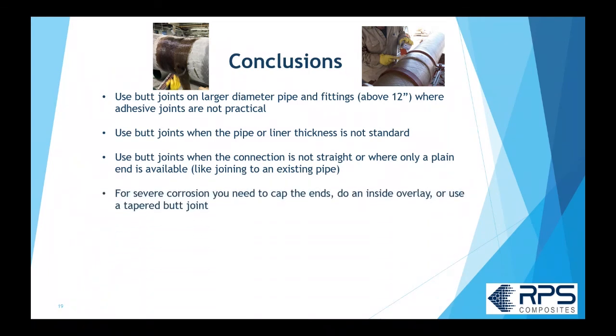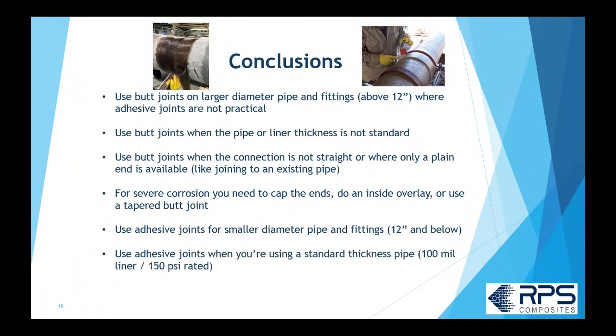If you have severe corrosion, you probably need to cap the ends or do an inside overlay or do a tapered butt joint if you're going to use a butt joint system. Adhesive joints are more practical on small diameters, so 12 inch and below, they're going to be much less expensive, much quicker, and much more reliable once you're trained on how to do it. The adhesive joints, you remember, you have to use that standard thickness pipe, so typically 100 mil liner and 150 PSI rated. That's going to cover you for quite a wide variety of services. If you look in our corrosion guide, there's a lot of services that would be applicable to that standard 100 mil liner.